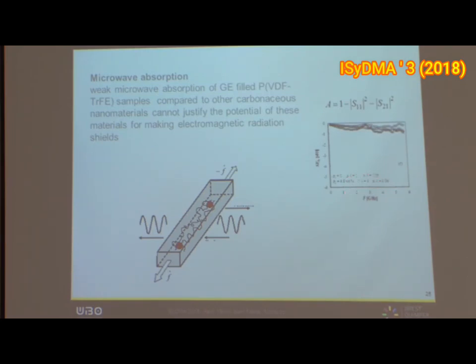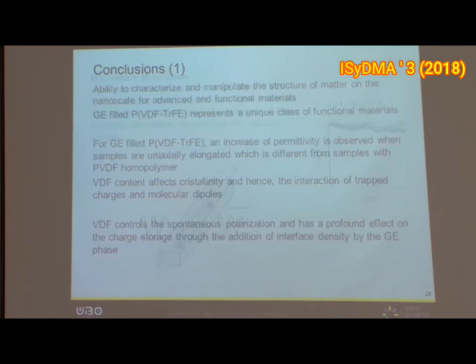This kind of result is very poor, in fact. So I would conclude that if you want to use PVDF-TrFE with graphene, it's not very good. You can have much more significant results using carbon black particles, ferrite, metallic and magnetic particles, but graphene is not good. This is an interesting result, but not for microwave absorption.